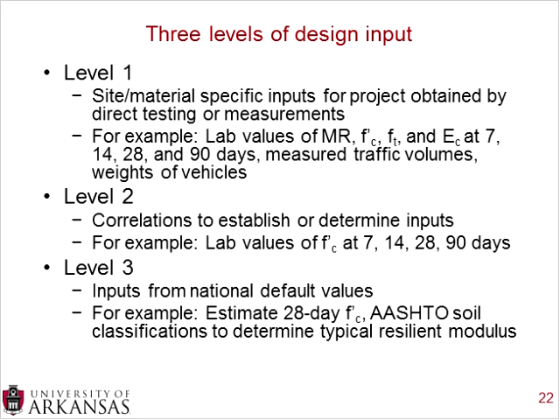which is modulus of rupture, or the flexural strength, F'c, which is the compressive strength, F_t, which is the split tensile strength, and E_c, which is the static modulus of elasticity at 7, 14, 28, and 90 days. You also have the measured traffic volumes and the weight of vehicles. So you have a lot of details at level 1. You're putting in a little more effort up front to get more details and more analysis in, which will take a little more investment up front, but in theory you're getting a better design out the back.